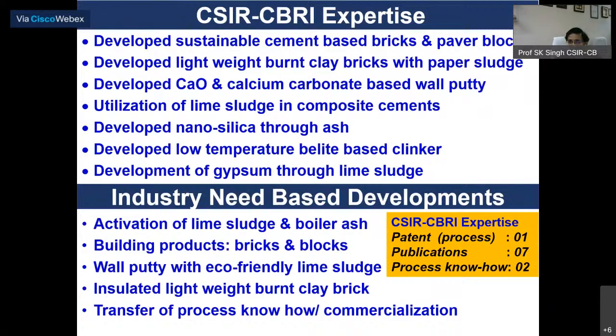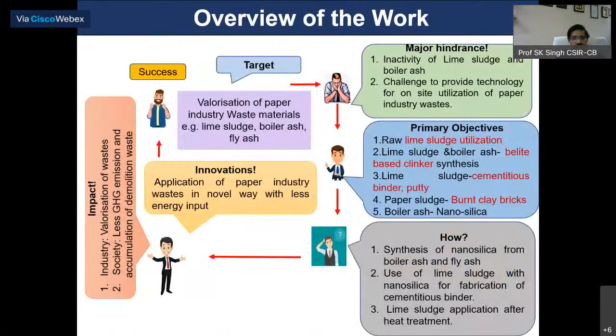Also we have developed nano silica, and belite-based clinker, meaning cementitious binder. Also recently we have worked on gypsum from lime sludge. With this technology, we have a lot of publications and process know-how, and we have filed patents. One is under acceptance and another is under process. So we understood the problem of the industries, and worked on different fronts with my team. We have looked at as-received lime sludge in building products, and at treating it, converting it into synthesized binder, putty, burnt clay brick, and nano silica. All those efforts have been carried out.